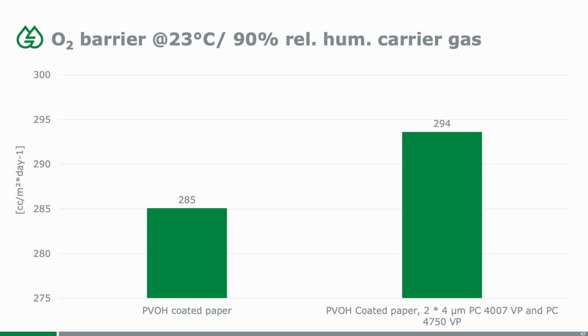So here in this chart, we look at the O2 barrier at 23 degrees centigrade, and we see that the PVOH coated paper on its own is at 285. If you then coat it with a two-layer system made from PC4007, followed by a top coat made with PC4750, you see that the oxygen barrier is not affected by the coating. So 285 or 294, that is literally the same result.